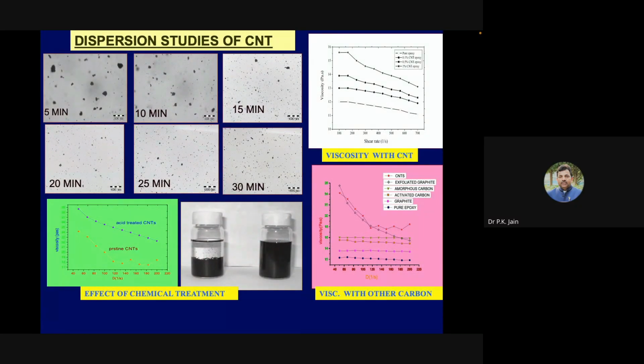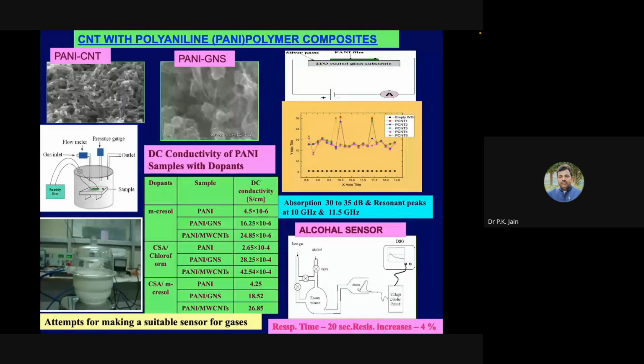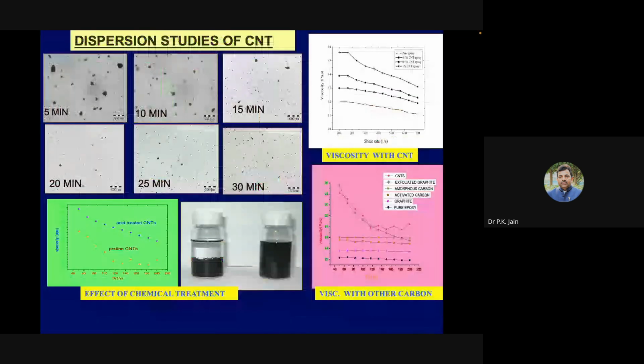In a polymer matrix, how to sonicate it, how to make it into that, that is the trick of that. You have to sonicate it into a particular solvent and then disperse it into a polymer. Otherwise, if you don't do sonication, we did a study of 5 minutes, 10 minutes, 15 minutes, and 30 minutes. And we found that a lot of agglomerate particles are there at the low timings, but as you increase the timing, those particles will be well dispersed. Is that question answered? Is that okay? Or do you still have some questions?